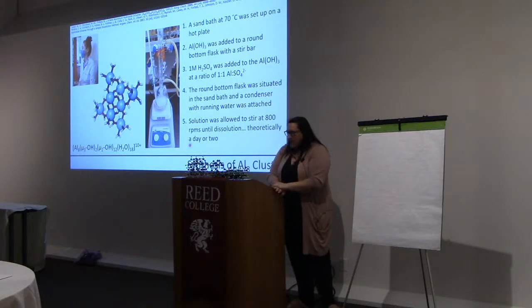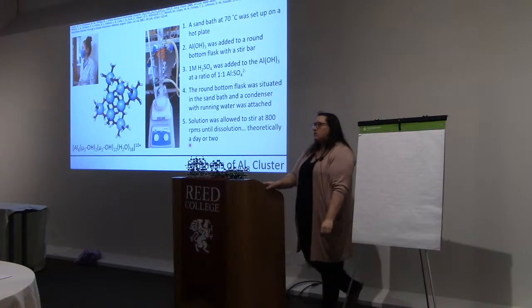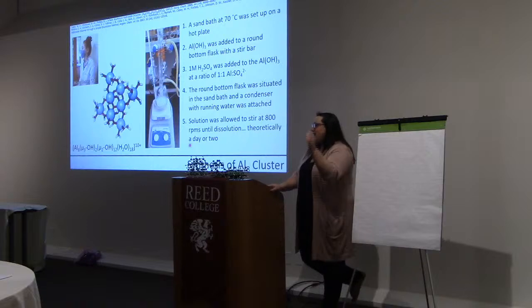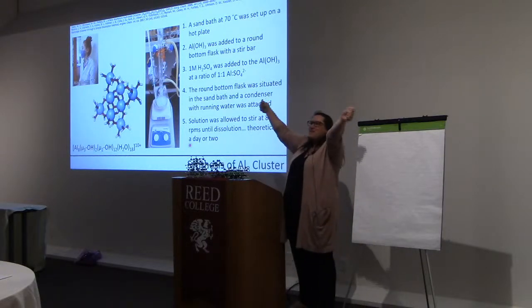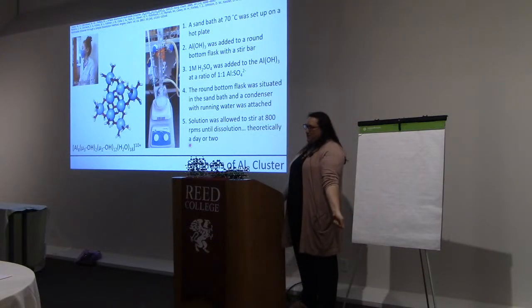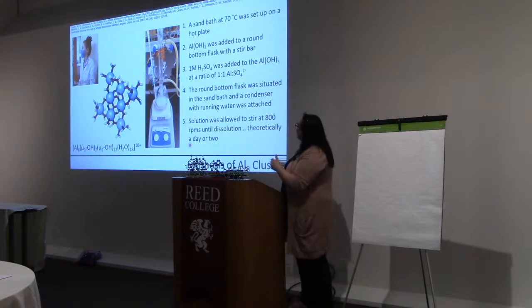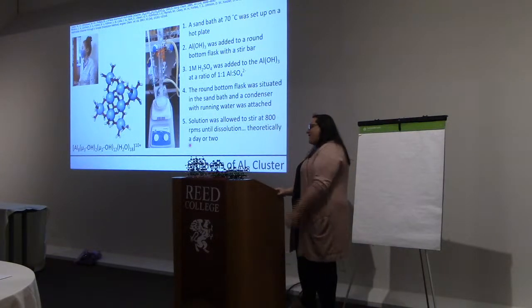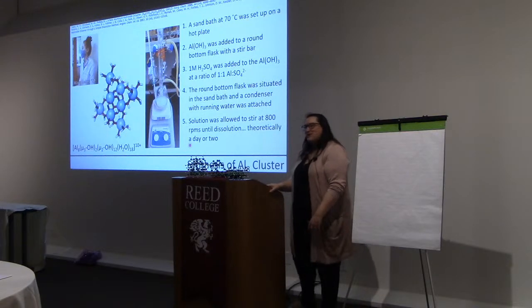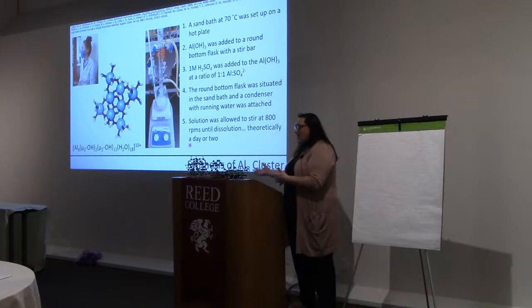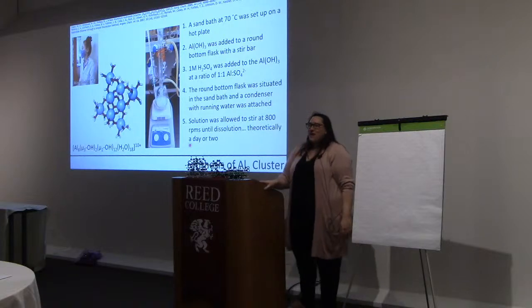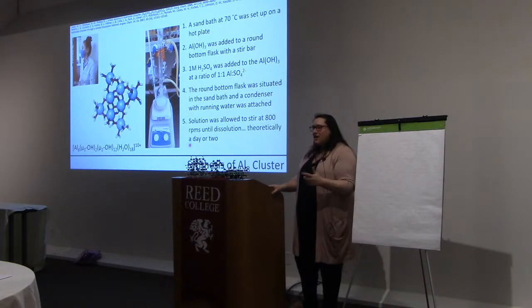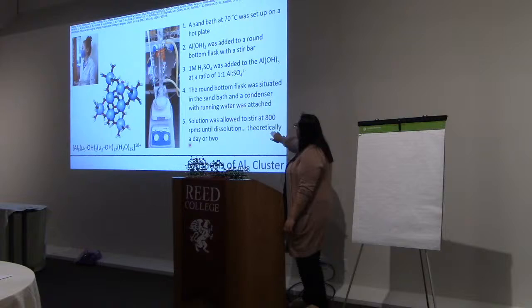The first publication of this cluster was in 2005, and the synthesis was that they mixed it up, put it in the refrigerator, and 3 years later they found 1 crystal, and when they did the crystal structure of it, it was something brand new, and they published it, right? Not necessarily repeatable. So then around 2017, there's a more reproducible, larger yielding synthesis that some of my colleagues and even I am on this paper were able to make and analyze, and then my student at SOU has,